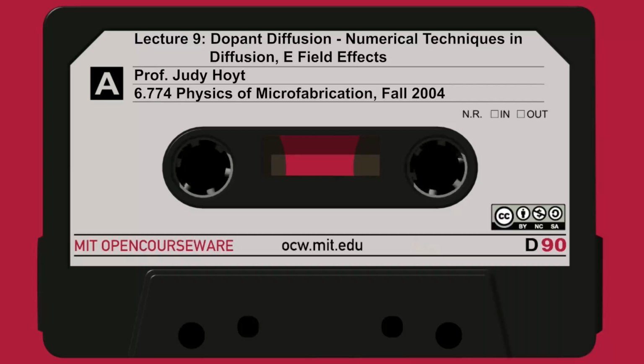This blue line is meant to represent the diffusion profile of electrons, let's say. So the electrons and holes diffuse more rapidly than their associated donors and acceptors. Because of that more rapid diffusion, the profile for electrons will be a little bit deeper. They'll diffuse sort of ahead of the dopant that they're associated with until they reach some steady state condition where the drift flux from the internal electric field is going to balance the diffusion flux.